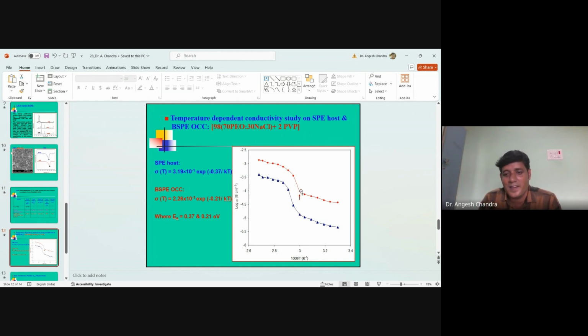And below this melting point temperature, we calculated the activation energy by using the Arrhenius equation, and we have found the activation energy is 0.37 eV in case of SPE host and 0.21 eV in case of BSPE OCC. It means the resistance decreases, and this lower activation energy indicates that this can potentially be used for solid state device fabrication.